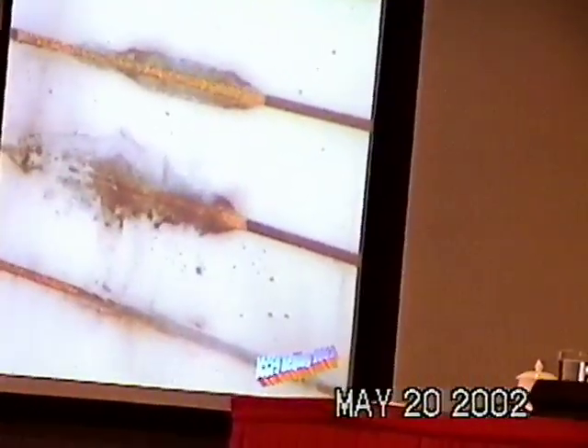Now, for an experimental proof of what I said about the calorimetry and the difficulties in having calorimetries is what we found at the end of an experiment we did in Frascati. We found the cathode like this. As you can see, the cathode burned. It's not just burned, but in some way it blows up and deposits again on the cold substrate. In this case it was aluminum.